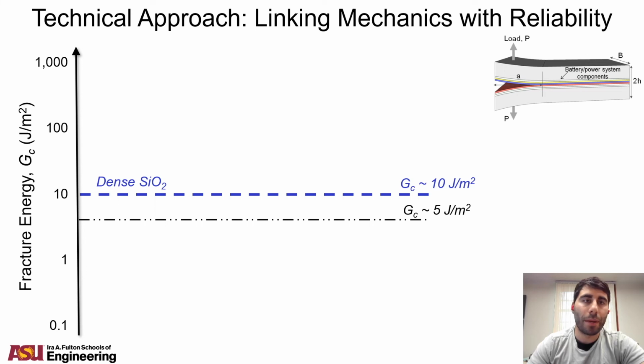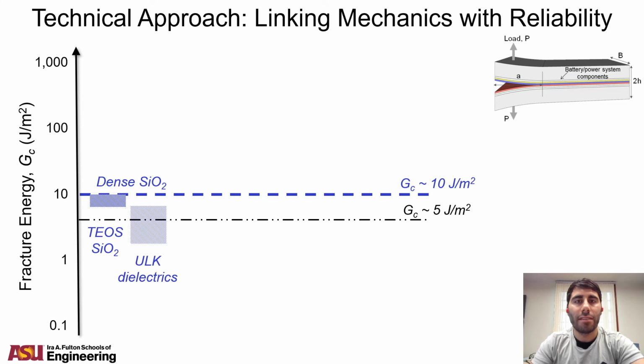So in terms of thermomechanical reliability, one of the key metrics is fracture energy. That is the amount of energy per unit area that it takes to break apart a material. And values that are below 5 joules per square meter indicate that these devices or systems are likely to be susceptible to failure during operation. This plot here shows fracture energy logarithmically on the y-axis. Glass is right around 10, and if you increase the porosity, the fracture energy goes down because there's fewer bonds.